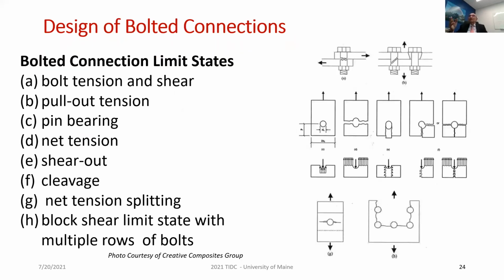For example, here on the top I'm showing different modes of failure of a single bolt. The bolt can fail in tension or shear. The single bolt connection can fail in pull-out tension, pin bearing, net tension, shear out, cleavage, and net tension splitting, which are depicted in the figure on the right-hand side. If there are multiple bolts, you get block shear, for which you have to prescribe the failure perimeter or failure mode. Based on that, you can calculate the strength associated with it.